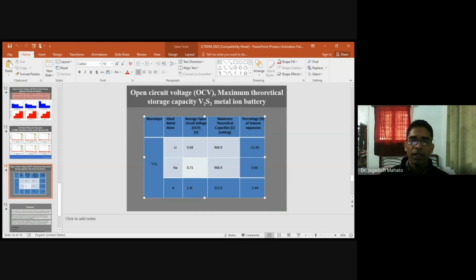And the maximum theoretical capacity for lithiated V2S2 and for sodiated V2S2 is 968.9 milliampere hour per gram. But for potassium, it is quite low, 322.9 milliampere hour per gram. And we also checked the change of volume expansion percentage, and it is within a reasonable limit. So from this, we can say that this V2S2 two-dimensional monolayer can be used as a potential anode material for lithium-ion and sodium-ion batteries.